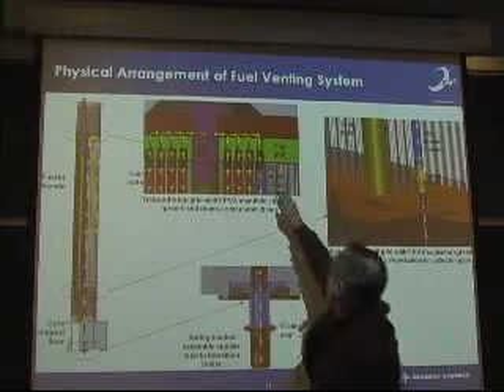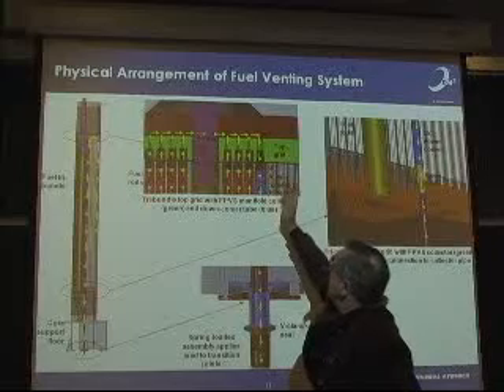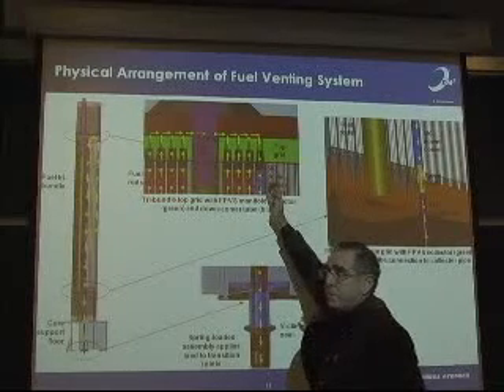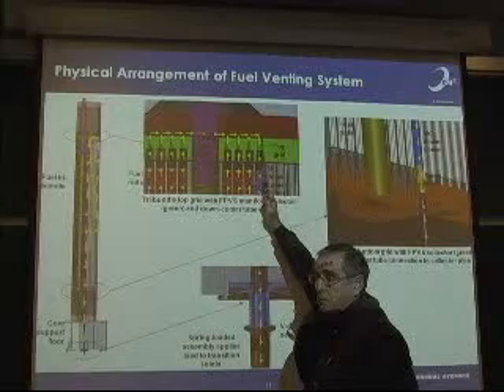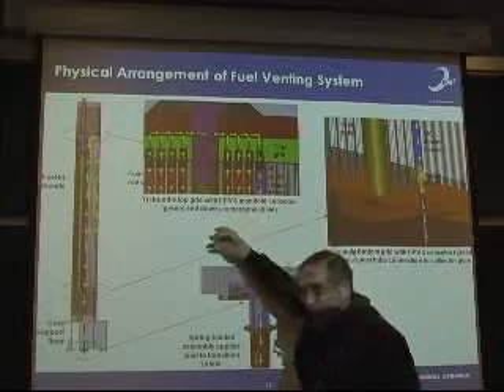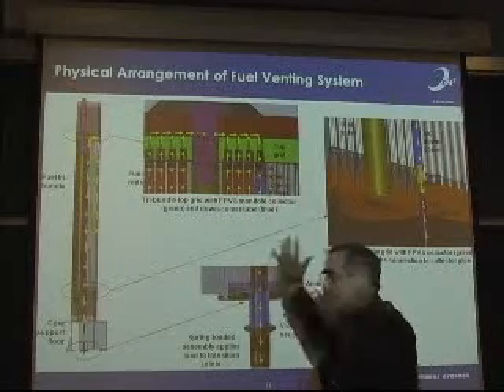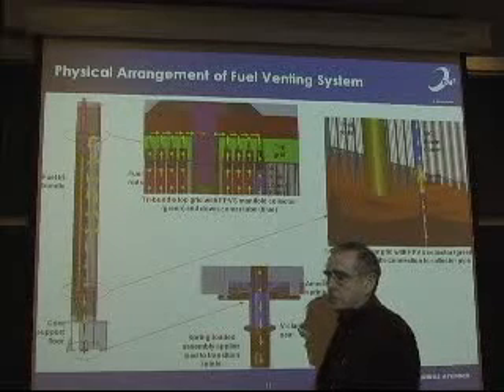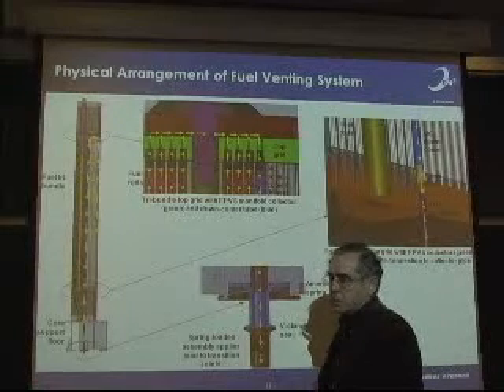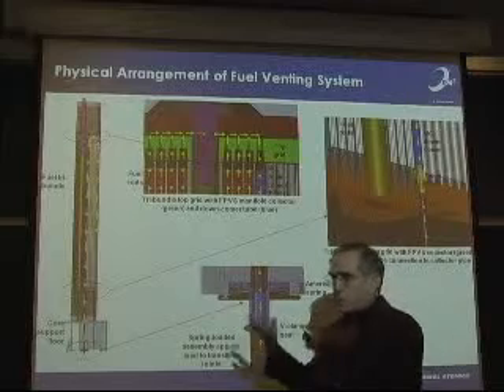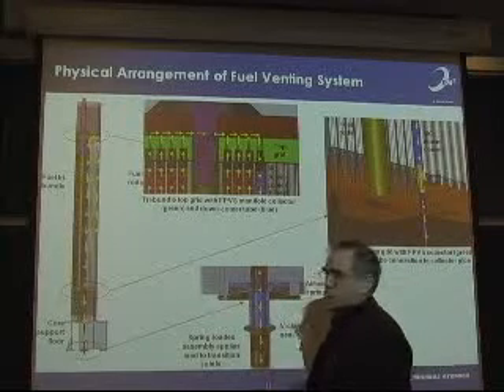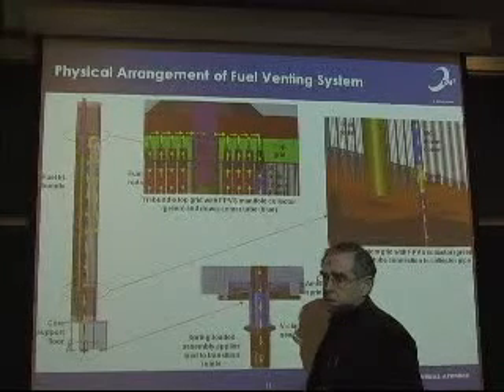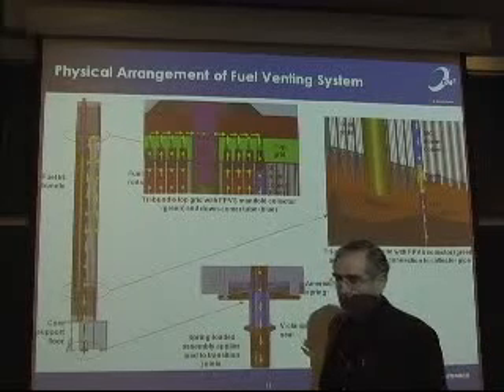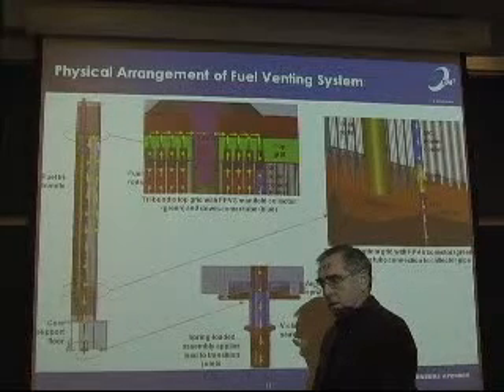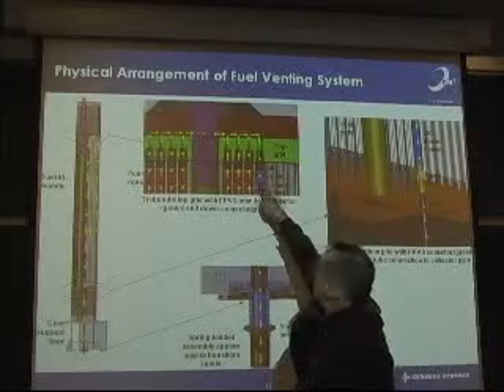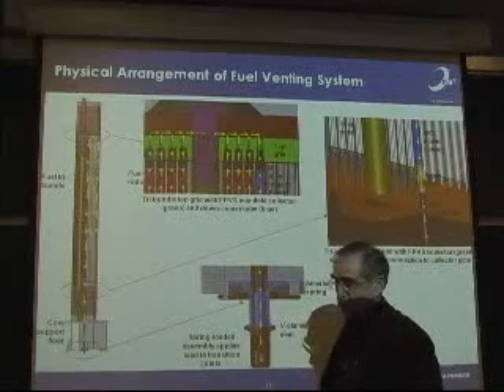Yeah, these are basically fission gases, but with a vented core, we don't have to have hermetic fuel cladding. We can allow leakage, and cracks and stuff are going to occur. There's going to be pinholes, especially with silicon carbide composite. So we allow quite a bit of helium leakage. We separate it out in the helium purification system and return it. So, that's mixed with the coolant, the fission gas. Inside the rods only. They do not get into the primary system.